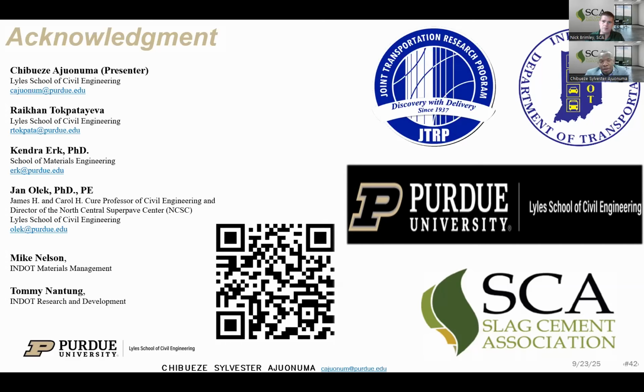Okay, because of time constraints, I didn't present the study we did on the microstructure of the concrete mixtures. But when we evaluated the microstructure under the optical microscope and then SEM, we found a reduction in the micro cracks with the SAP, showing improved microstructure and improved hydration. Although it reduced the air content, which was also what we saw from the fresh properties, there was a drastic reduction in micro cracks in the concrete mixtures. This can also help to improve the interfacial transition zone in the concrete, so improving the durability and mechanical properties.